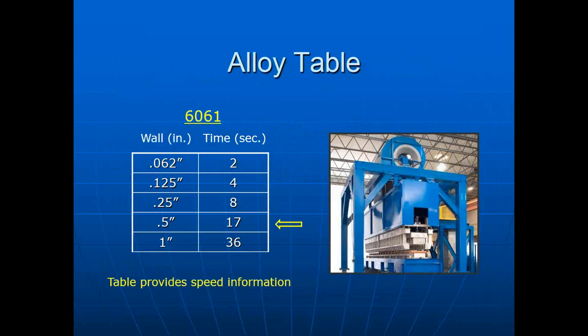Now, I can also verify that. I can verify the temperature in with either a contact thermocouple probe or with an infrared probe, and I can measure temperature in and measure temperature out. But that information is also contained in the alloy table. I have to run at a speed where I am spending 17 seconds inside the quench if I'm running a half-inch wall to assure properties.